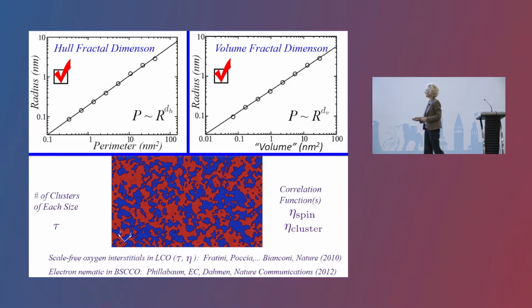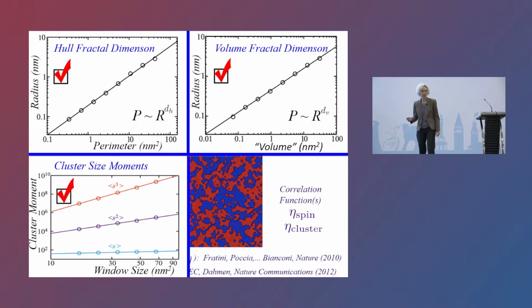We also take a histogram of cluster sizes, similar to the analysis done here by Bianconi's group. So here you would look at the number of clusters that are a particular size. We've analyzed here actually the moments of the cluster size distribution, but it's the same idea. You count how many clusters are of a particular size. This is also nicely power law.